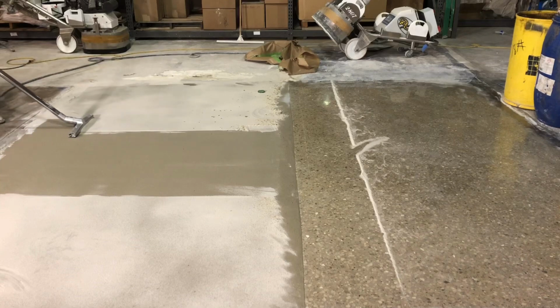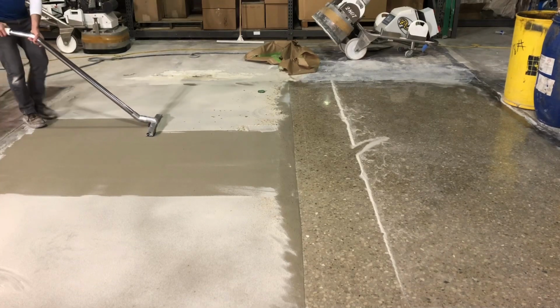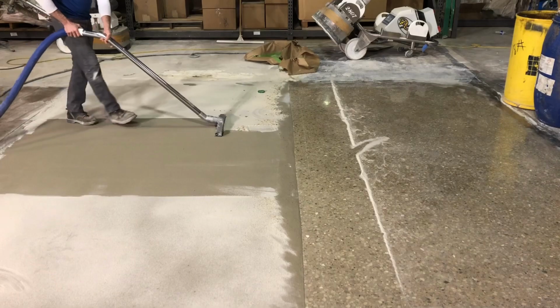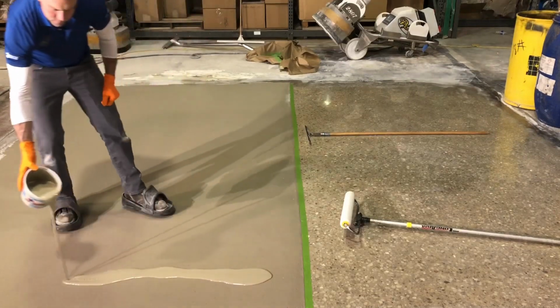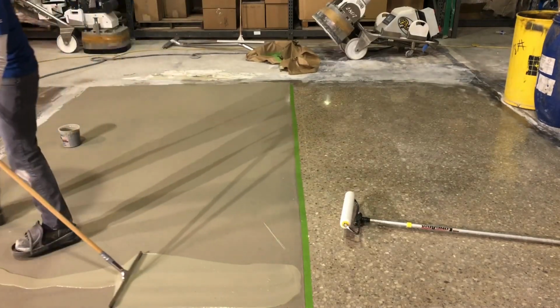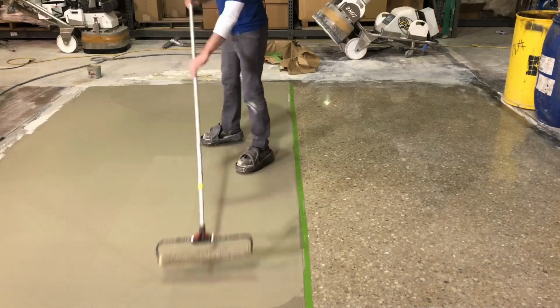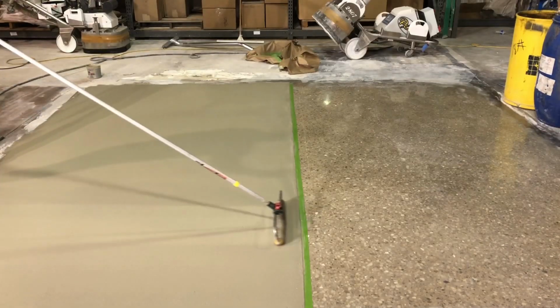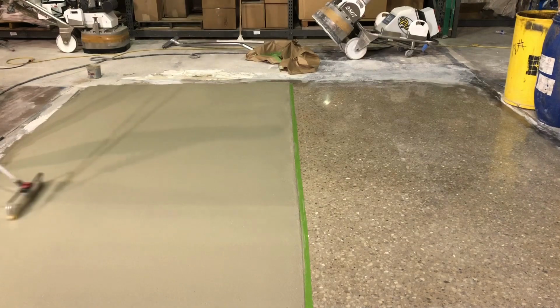Once the floor had been allowed to cure for at least 8 hours, in our case about 16, the floor was vacuum cleaned. Therefore, the only sand that remained would be trapped inside the epoxy. The next coat was an epoxy seal coat, applied at approximately 7 mils. The epoxy seal coat is installed to lock down the sand. At the top of the epoxy body coat, there's still going to be exposed sand, which is porous, as well as any porosity or air that was trapped. The idea of the seal coat is to lock everything down and together, so that the top is going to be very durable and basically resilient at that point.